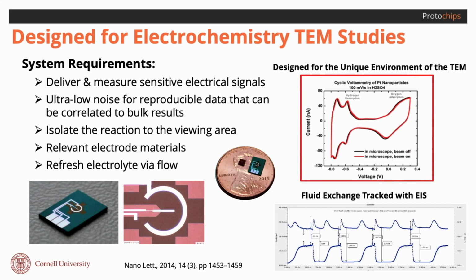This platinum sulfuric acid cyclic voltammetry plot demonstrates that the electrochemical measurements are not appreciably affected by the TEM's electron beam. The red line indicates that the beam is on, and the black line is the same experiment with the beam off.